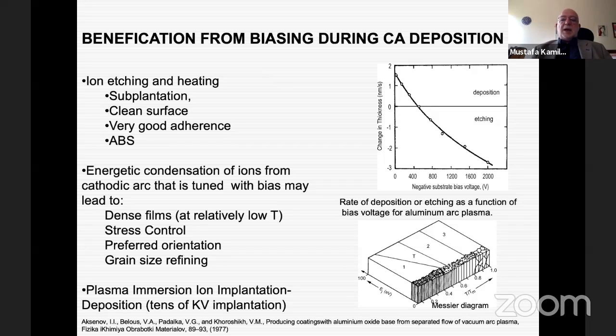So we ion etch the surface by application of a high voltage. Then when we reach the required deposition temperature, we lower the voltage and start the deposition. And by controlling the magnitude of this voltage, we can tune the density of our coating, we can control stress, we can control preferred orientation, we can even end up with grain size refining.